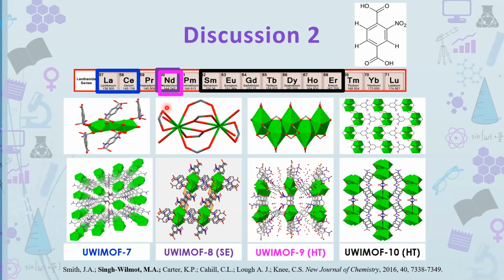The other structures I wanted to show you were with the nitroterephthalic acid. We got a series of compounds when we go across the lanthanide series: lanthanum and cerium would give us UWI-MOF 7, and neodymium would give us UWI-MOF 8 and UWI-MOF 9 under different conditions. So slow evaporation conditions would give us UWI-MOF 8, but hydrothermal conditions gave us UWI-MOF 9. And UWI-MOF 10 we got here with samarium to erbium.